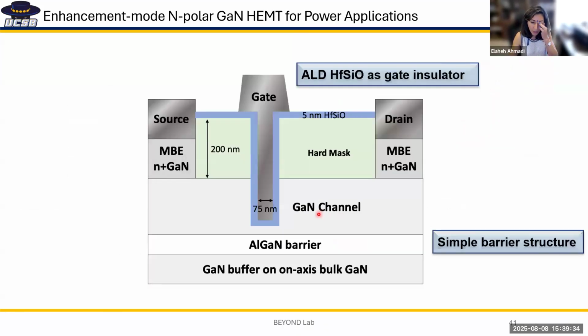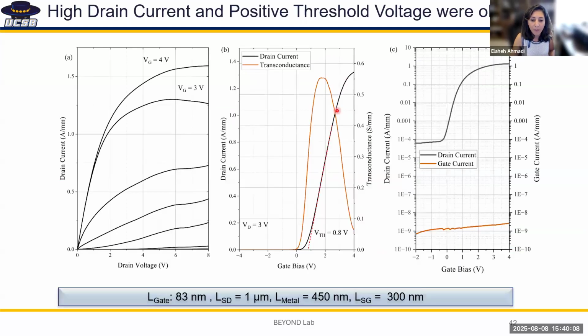So the approach we took was we used the deep recessed structure, basically the same process that we have developed, which is nice. It's more integration friendly, and the only difference is basically here you need a deeper etch to make the gallium nitride channel thinner under the gate. But we are using the same simple barrier structure, and we are using the ALD hafnium silicon oxide as gate insulator that we developed in our group. And so using this simple processing, we for the first time actually demonstrated E-mode behavior on nitrogen polar GaN HEMT,